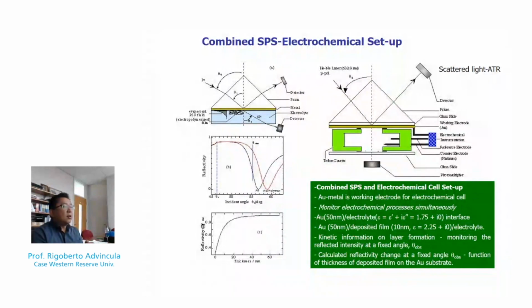That means that the whole thing will allow us to measure the thickness changes of an electrochemistry or electrodeposition experiment, or will allow us to monitor the electropolymerization or even the redox kinetics, reduction oxidation kinetics of a dielectric layer that is electrochemically active on gold. So this is already a hyphenated technique that we have reported in many cases.